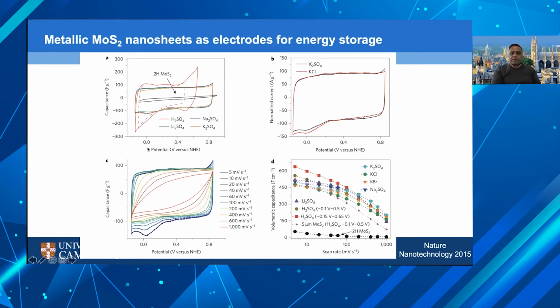If you plot the capacitance as a function of voltage, the CV curves, we can see that these are nice square curves, and we get nice capacity for lithium, sodium, and potassium. For the protons, we can see nice redox peaks, as one would expect. And there's good rate performance of these supercapacitors, and we're able to achieve volumetric capacity on the order of 500 farads per centimeter cubed.